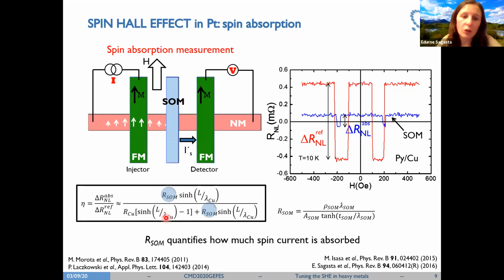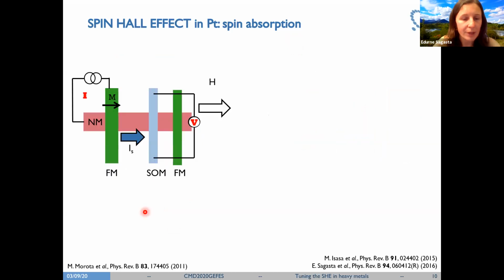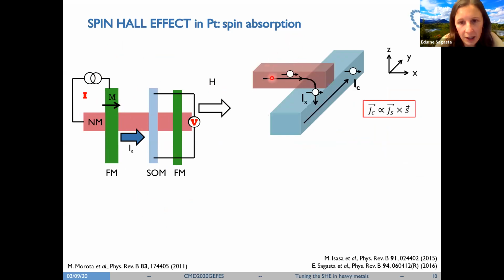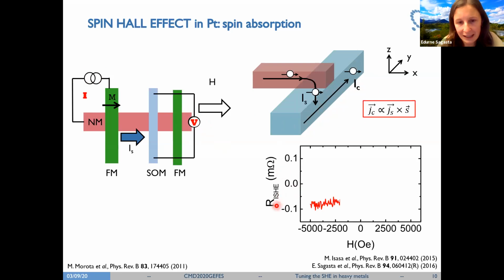Once this absorption has been quantified, we can jump to the second measurement, where we will measure the inverse spin Hall effect. So now we apply the magnetic field along the copper axis or copper channel direction, so that the spin current that is injected also points in that direction. The spin current will be absorbed by the spin orbit metal, platinum in our case, and due to the inverse spin Hall effect, it will be converted into a charge current, and therefore will give rise to a voltage drop that we can measure. By dividing by the current, we extract an inverse spin Hall resistance.